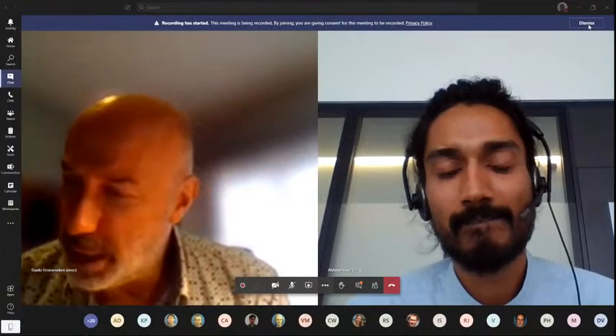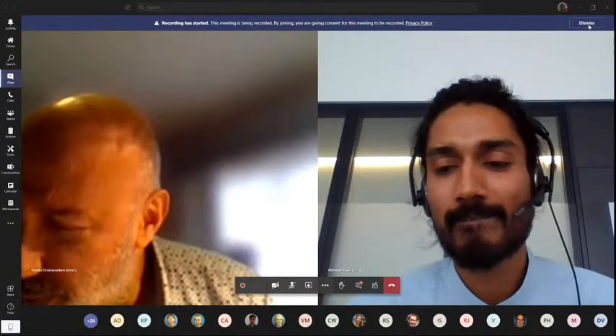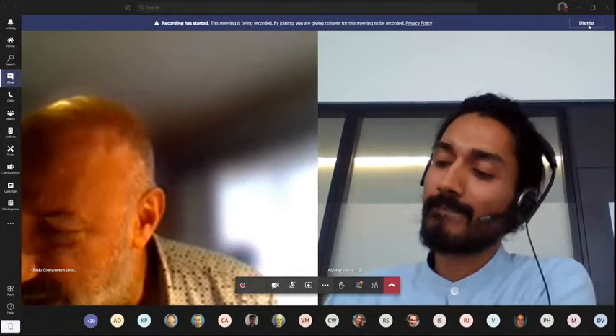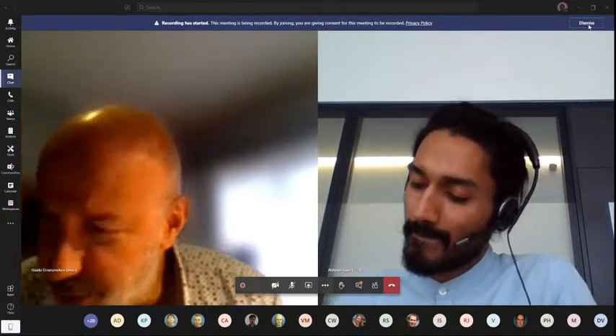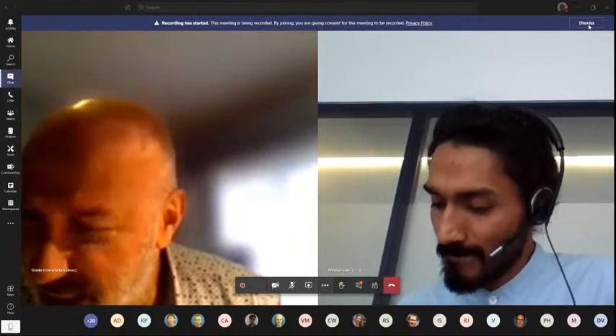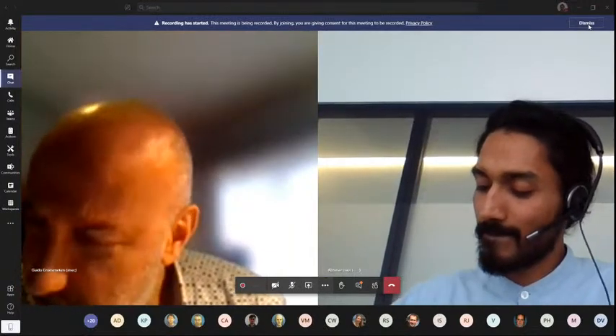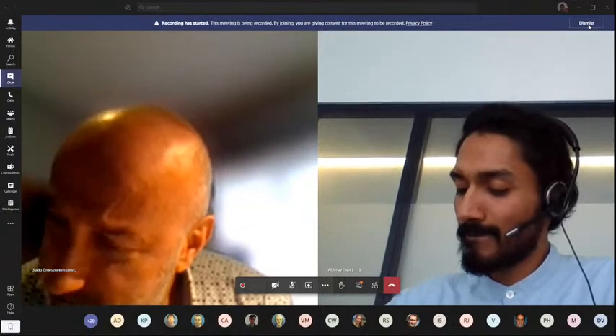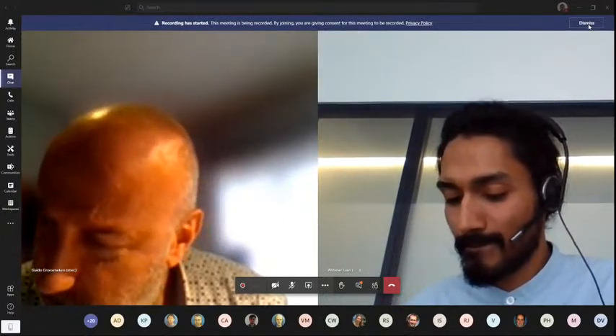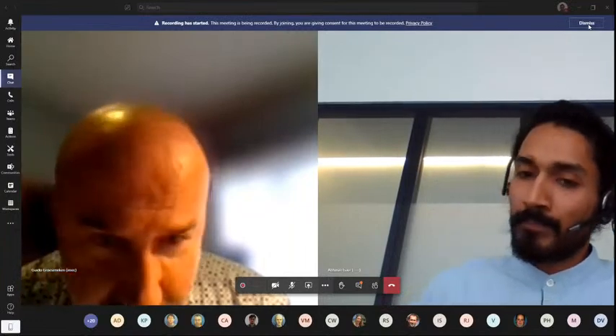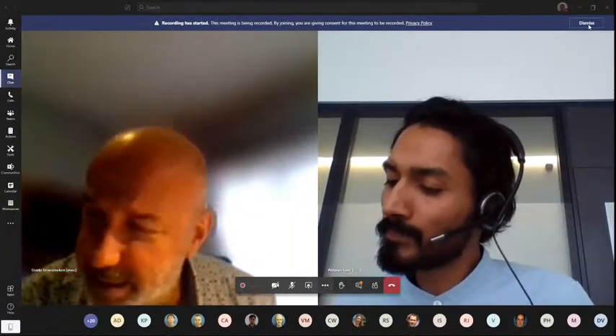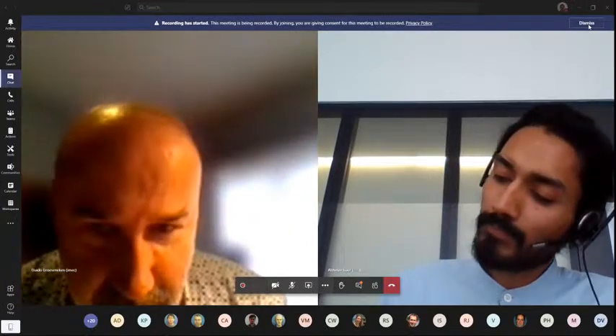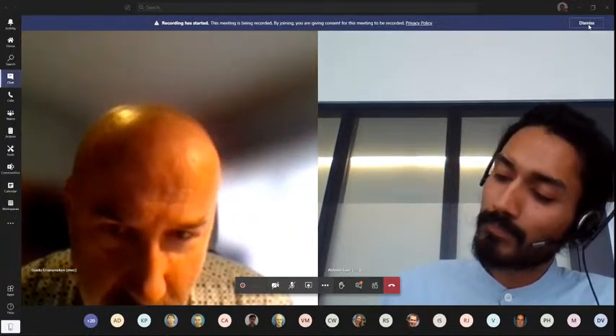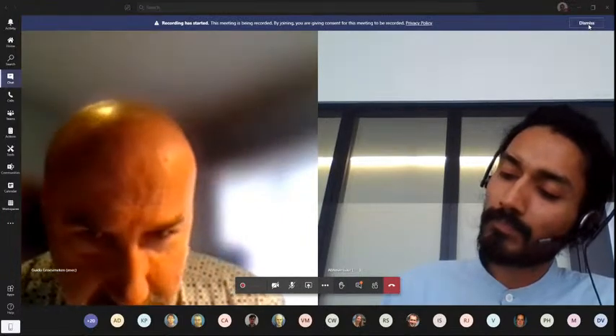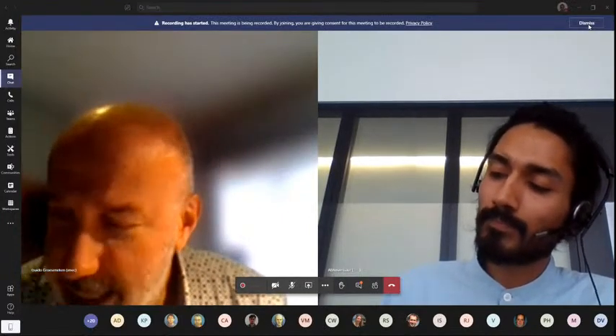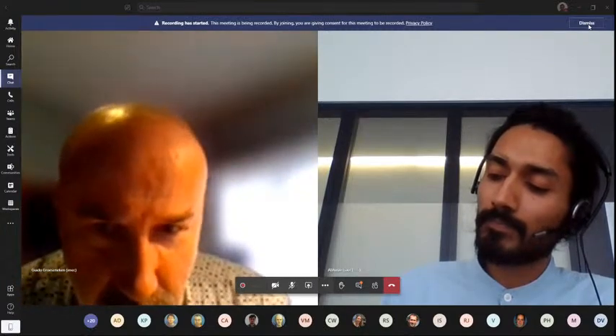My first question is about the dispersion characteristics that you show in your chapter 5, figure 5.8, and also the mobilities that you extract from ID-VG characteristics, which is in figure 5.14. In these two, one you extract mobility from dispersion, the other from the current characteristics. And in both cases, you find that the mobility is peaking at 8 nanometer hafnium oxide thickness and is lower for both thinner and thicker oxides, 4 and 12 nanometer. I was wondering if you have thought about what could be the reason for that.